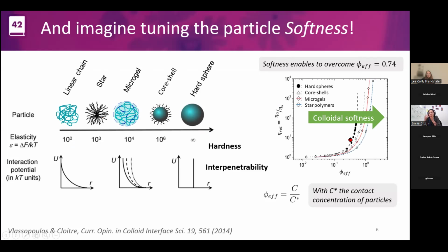And then we will also see that because of this ability to deform these particles, the space will be able to be packed much more than when you had just hard spheres, because hard spheres have an interaction potential that diverges to infinity. When you bring them next to each other, they cannot deform, so it's just impossible to make them compress, let's say. So what happens when you put these particles that are deformable is that you can tune this divergence of the viscosity with the softness of the colloids.